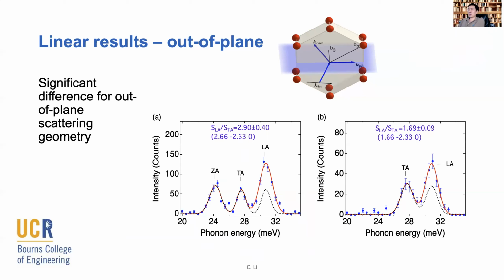Here I'm again plotting our measurement versus our calculation. You can clearly see that in this case, the TA and LA modes do not agree with what the existing scattering theory tells us. There's definitely something missing. We're definitely missing the polarization of the photon that might be involved in the transfer of angular momentum during the scattering process. We tried that for several different K and K prime points through the Brillouin zone, and we see similar behaviors.